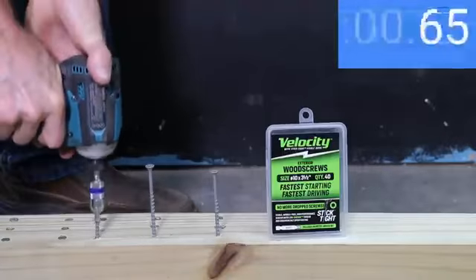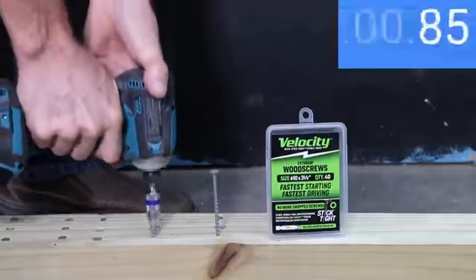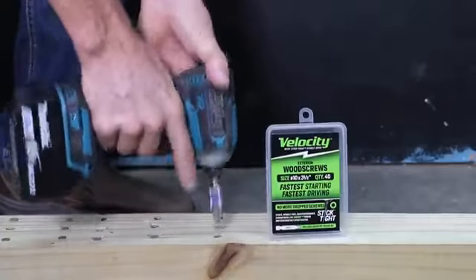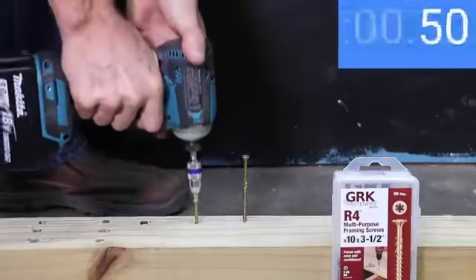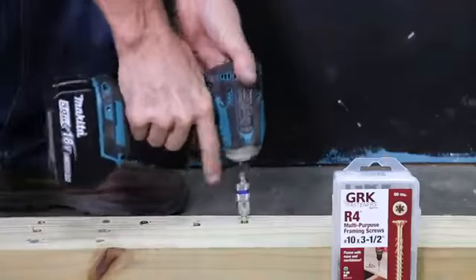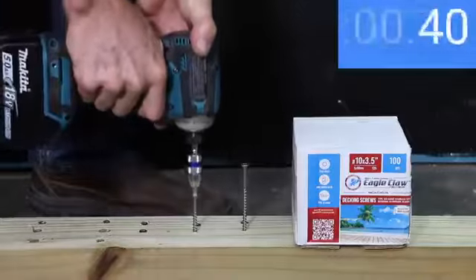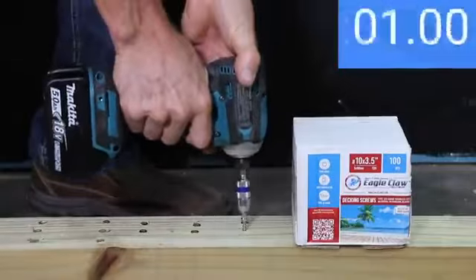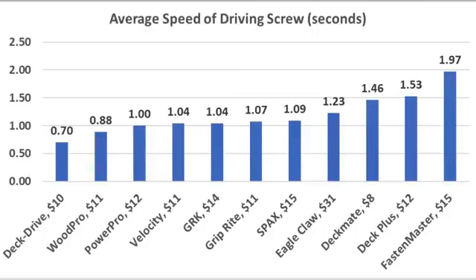And the Velocity screws were slightly faster to install than the SPAX at 1.04 seconds on average. And the GRKs move into a tie with Velocity at 1.04 seconds. And the stainless steel Eagle Claws were hammered into position at 1.23 seconds. If you're looking for the fastest screws to install, the Deck Drive is the fastest at 0.7 seconds, WoodPro 0.88, PowerPro 1 second, and Velocity and GRK 1.04 seconds.